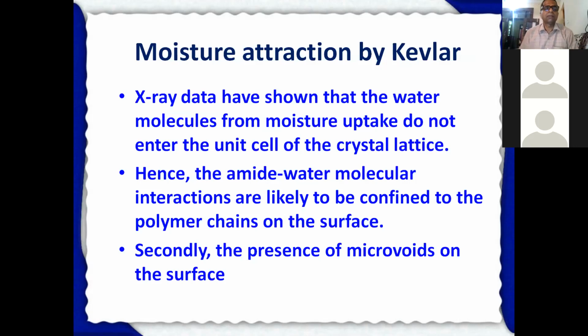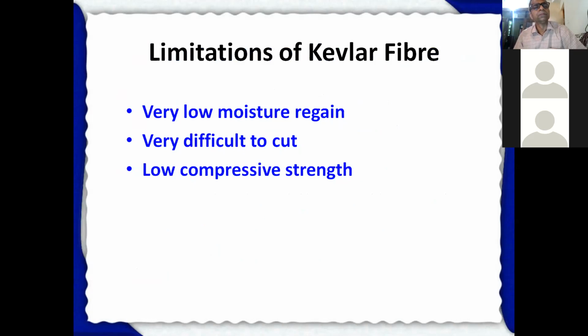Moisture attraction by Kevlar. X-ray data have shown that the water molecules from moisture uptake don't enter the unit cell of the crystal lattice. Hence, the amide-water molecular interactions are likely to be confined to the polymer chain on the surface. Secondly, the presence of microvoids on the surface is responsible for attracting the moisture. Otherwise, there is no means of strong attraction of water inside the Kevlar fiber.